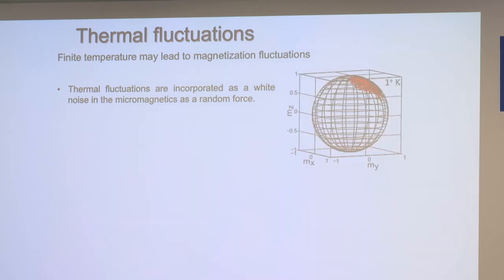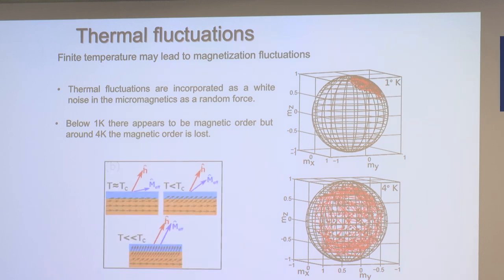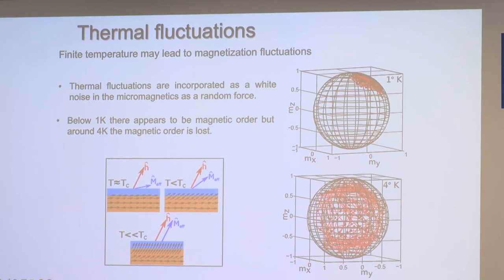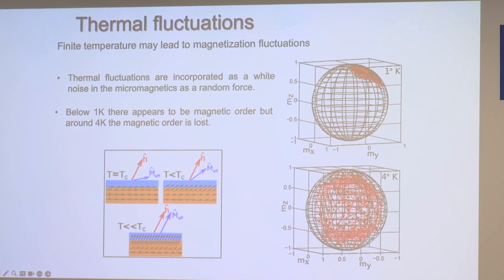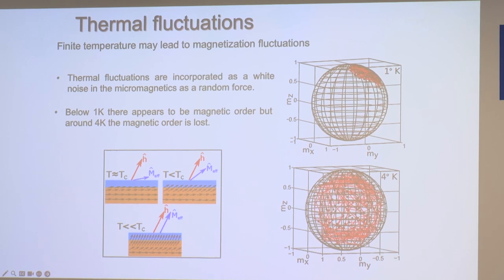The other thing to mention is that there is this temperature effect, and this is somewhat disappointing. It's good in the sense that having some sort of temperature effect is consistent with an onset of coherence in the surface state. We can model it with thermal fluctuations destroying the magnetization in the surface state at higher temperatures and having a coherent magnetization at low temperatures. This is nice in the sense that it shows that something is onsetting. If you measure YIG alone, you don't see any onset temperature effects at low temperatures. It's basically the same from 1 Kelvin all the way up to room temperature. The hysteresis size changes, but you never see features like this that onset or go away. So this is again consistent with a surface state, but why this onsets at 4 Kelvin and low temperatures, I don't know. It's interesting to me that this happens only at this temperature, but presumably it's some crossover between magnetic order and thermal fluctuations.